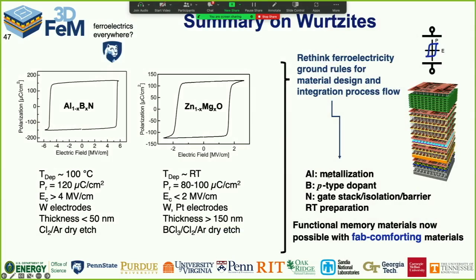Well, aluminum boron nitride in particular looks sterling. We use aluminum as metallization already in these stacks. Boron is the p-type dopant, and nitrogen is used in every gate stack. And we're doing some of this preparation at room temperature. It's all sub 400 degrees C. So we're growing the aluminum boron nitride from 200 degrees C down to room temperature. The zinc magnesium oxide, ballpark 100 degrees C down to room temperature. So we've solved the integration issue. We can do this material on tungsten plugs at relevant temperatures with relevant electrical properties.